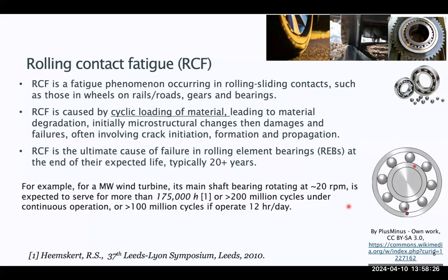So the expected bearing life is over 20 years. For example, for a megawatt wind turbine, the main shaft bearing normally rotates at less than 20 RPM, and is expected to serve more than 175,000 hours, or 200 million cycles under continuous operation, or over 100 million cycles if they operate 12 hours a day. This is what we expect, but as most people have heard, some megawatt wind turbine gearbox bearings fail in the very early stages of their operation, rather than serving for a very long time as they were expected.